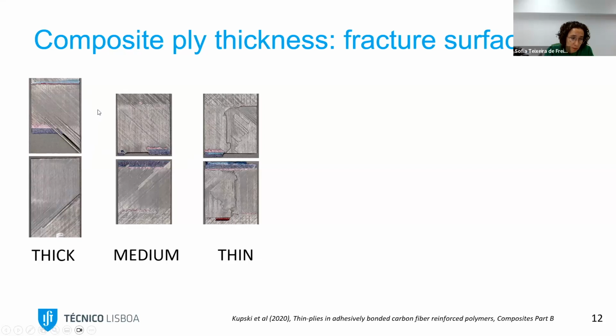What we also see is that if we look at the fracture surface in comparison with the overlap area, where we had the bond line, for the thick, this area kind of propagated further than the bond line. And as we decrease the thickness, the fracture surface was more contained only inside the adhesive layer region.